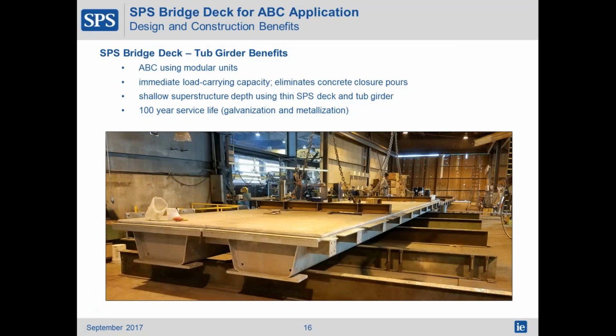Combining the exterior and interior modules, they were pre-attached in the shop as shown in the picture here. As well, this has immediate load carrying capacity as there are no concrete closure pours required between the modules. The overall depth of the superstructure was minimized by the efficient tub girder design and the thin SPS deck. The 100-year design life was achieved using a spray metallization on the SPS deck panels, while all other superstructure components were hot dip galvanized.